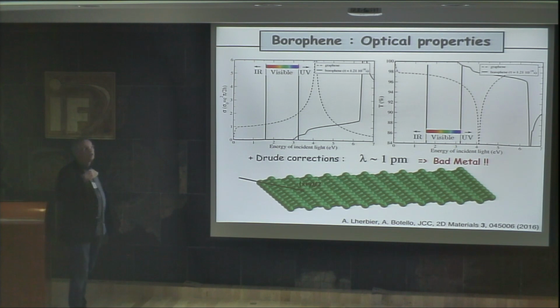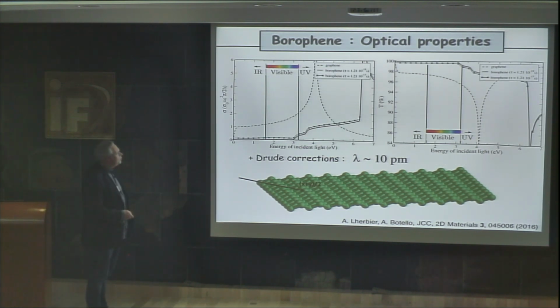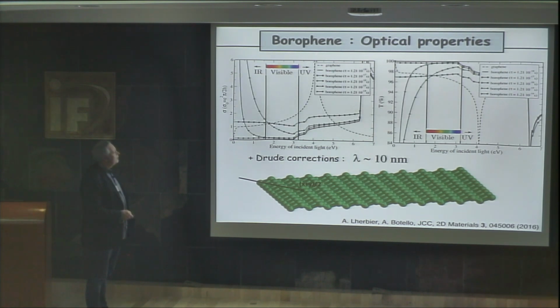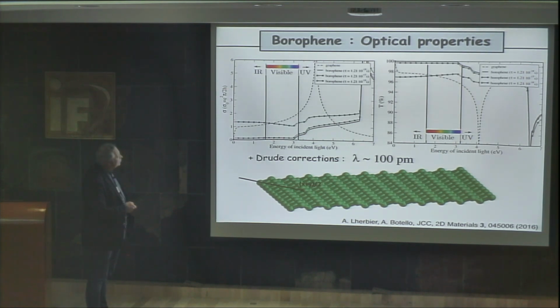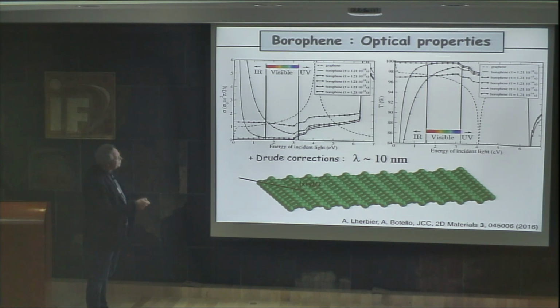We are trying to increase the value of the electronic mean free path in this model in order to go from a bad metal to a very good metal. If we improve the electronic mean free path from 1 picometer to, let's say, 100 nanometers, we go from a bad metal to a very good metal. You can see what's going on when we increase the value of this electronic mean free path. The transmission goes down and the optical conductivity goes up, and suddenly it goes down again, and the transmission goes up to 100%.